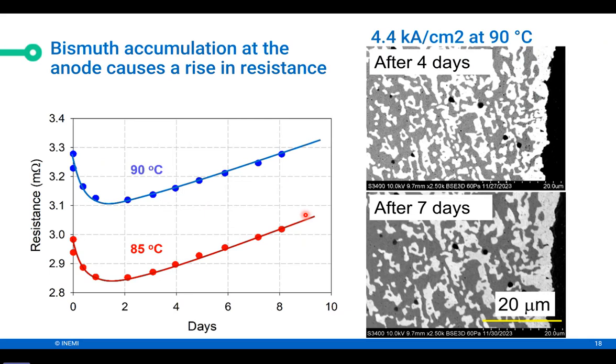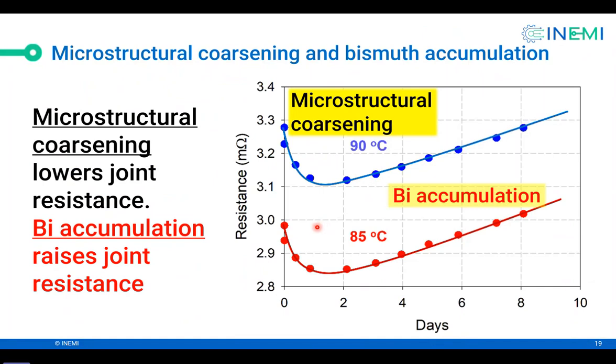It is because bismuth begins to segregate at the anode. So after 4 days, it's this thickness. After 7 days, it gets thicker. So that's why the resistance increases, because of the bismuth segregation at the anode. This is just a summary chart. So microstructural coarsening decreases the resistance. Once the structure becomes coarse, then the resistance goes up because of bismuth accumulation at the anode.